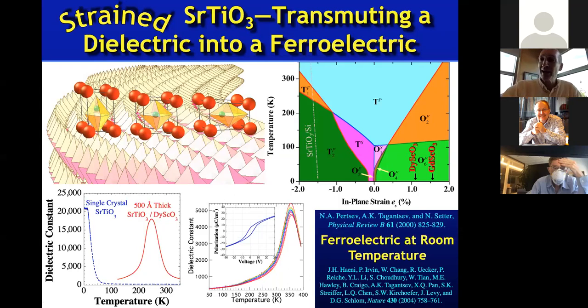But it goes into what Alex called a quantum paraelectric state with this very high dielectric constant. On the other hand, when we strain strontium titanate commensurately, so this film is 50 nanometers thick, you can see that there's now a nice, clearly defined peak in the dielectric constant. So it obeys Curie-Weiss law.